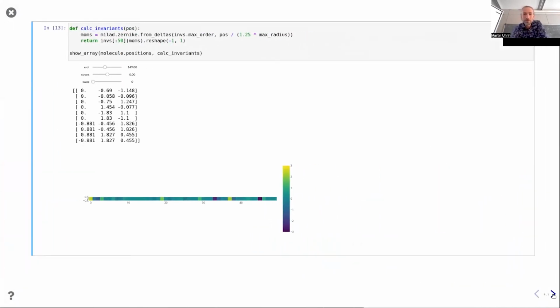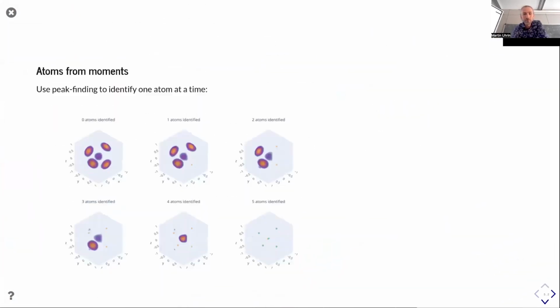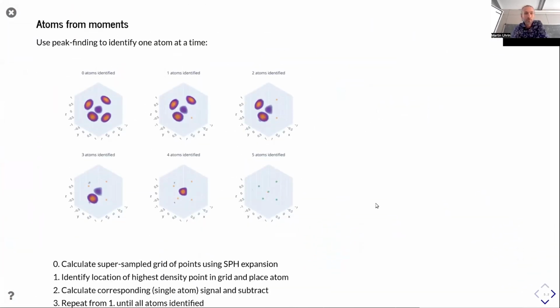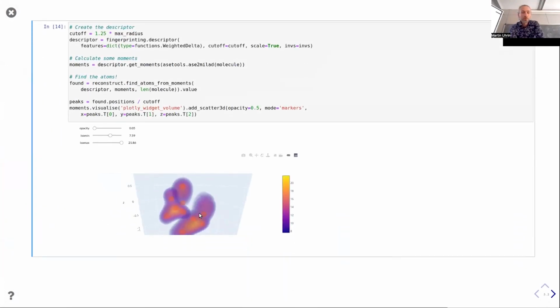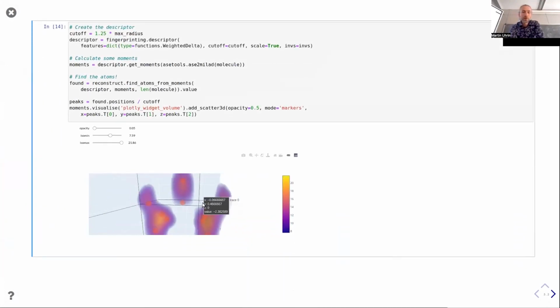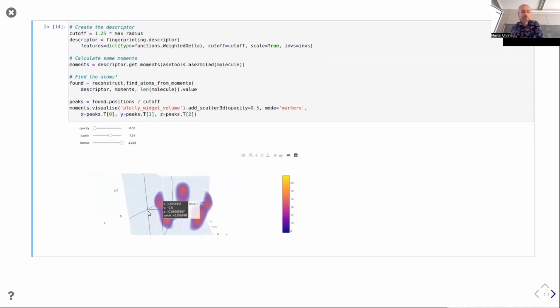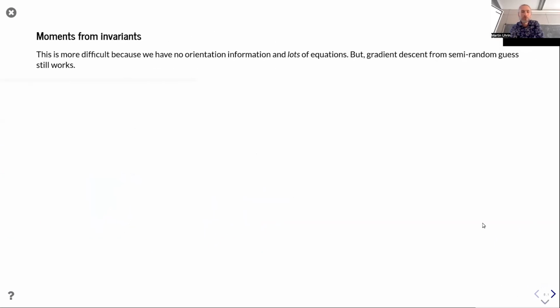show you these. So we're back to this fingerprint that I have, and now I need to go back to my atoms. So the easy part is effectively finding where the atoms are in this sort of signal, this rotation invariant, this permutation invariant signal. Wherever the peaks are, that's probably where my atoms are, and I can build an algorithm that iteratively finds one after another after another. So that's what this function is doing. It's basically taking the atom density and it's found these orange dots, which are at the maxima in this density, if you like. And that's indeed exactly where our atoms were from the original.